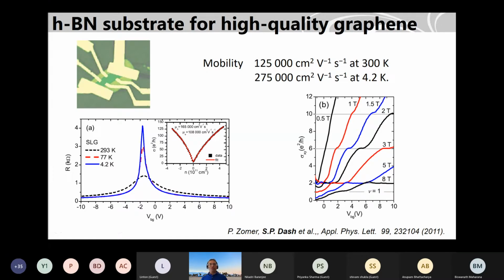So we have some annealing procedure to get this high mobility. So mobility we could get up to 200,000 at low temperature and 100,000 at room temperature, which is quite good. And as you see, we see this quantized Hall conductance at very low magnetic field, or even at 1 Tesla, you see this quantized conductance.